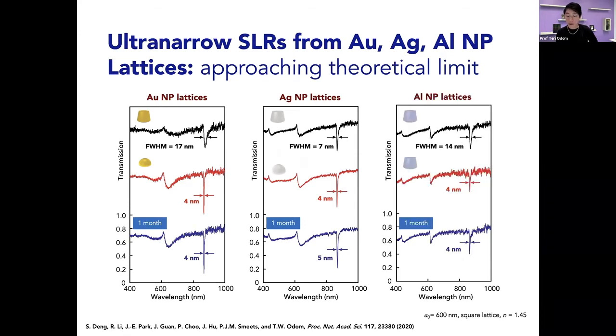We can do the same thing for silver nanoparticle lattices. The full width at half max is a little bit nicer from the beginning, but after the annealing, the particle reshapes and the resonance becomes really narrow. And even after a month, the full width at half max remains narrow, even without having to protect the silver nanoparticles with an oxide. And for the aluminum nanoparticle lattices, we also get an improvement in the SLR. But as you can see by the cartoon, we have less reshaping of the aluminum, but the internal structure results in these larger grains. And so this is why we also get this reduction down to about 4 nanometers.